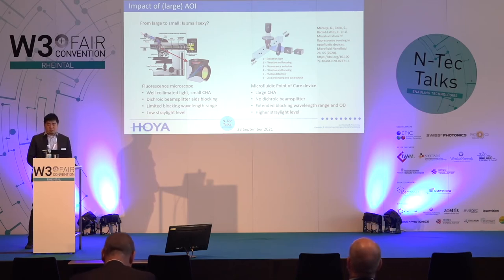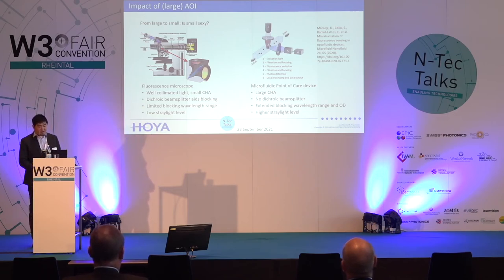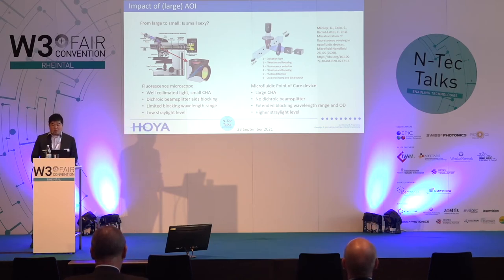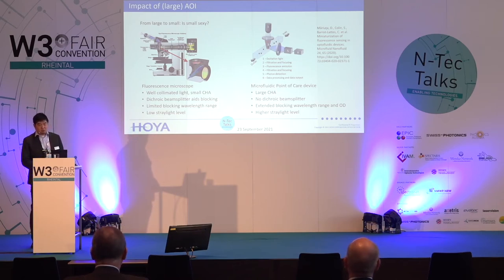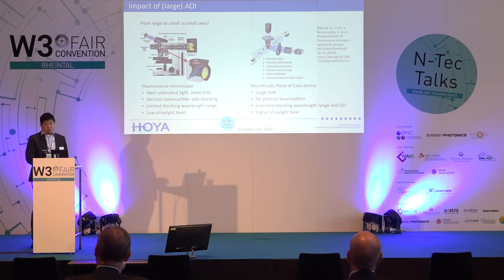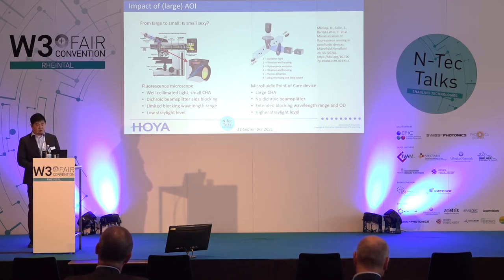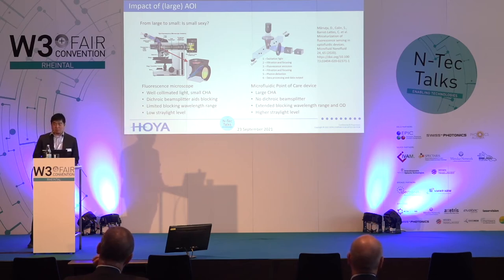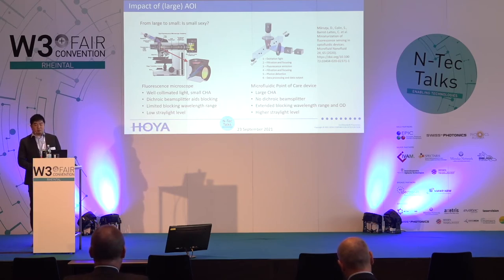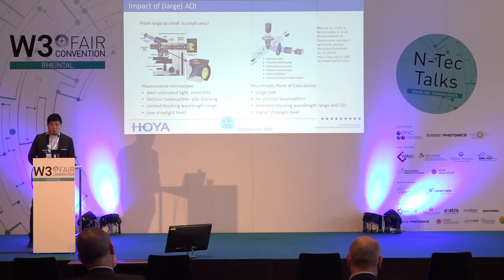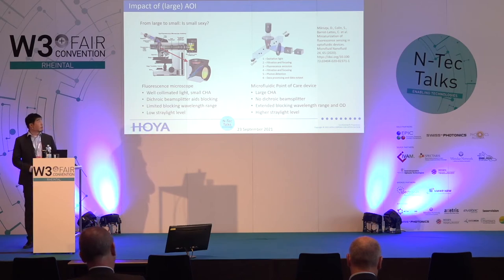What we recently see is that the same fluorescence technology is used in smaller instruments, like point-of-care devices, which have been especially fueled by the corona pandemic for the corona quick testing instruments. In these compact instruments, you have large cone half angles, and you can't use the dichroic beam splitter, because you need an extended wavelength range for your silicon-based detectors. Because the beam splitter is missing, a higher OD value is needed in the excitation. And because of the compact design, it's not very easy to control the stray light level. So that is definitely much more challenging when making good filters for very compact instruments.